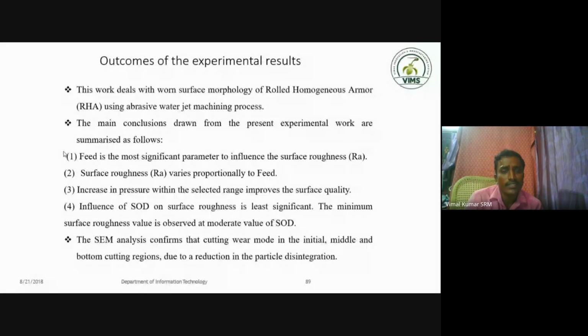The SEM analysis confirms the cutting wear mode in the initial, middle, and bottom cutting regions, due to the reduction in the particle disintegration.